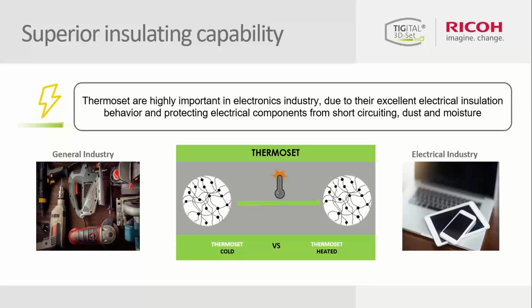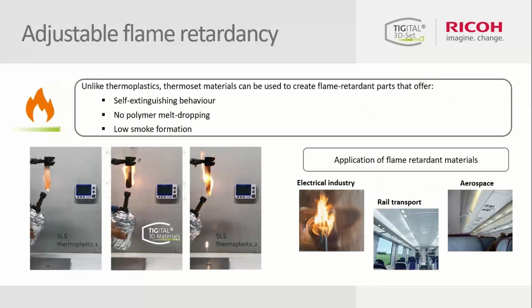And when we look at electrical application, an important feature of this material is its very good insulating properties combined with high dielectric strength, which, together with the fact that they can withstand sudden increase of temperature without losing their shape, makes this material a very good candidate for this type of application. And as Boris was mentioning before, water uptake, which again is an issue we can see with nylon material, for example, is very minimal with Thermoset. So again, this is another benefit for electrical application. And on top of that, this material can also be formulated with flame retardant properties.